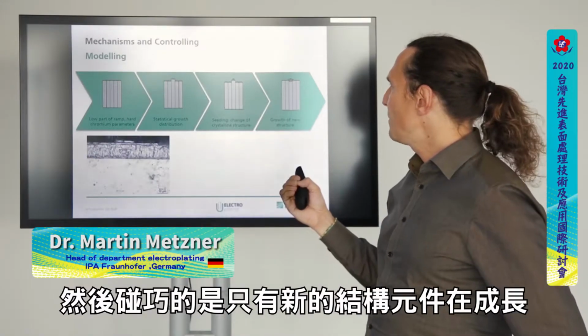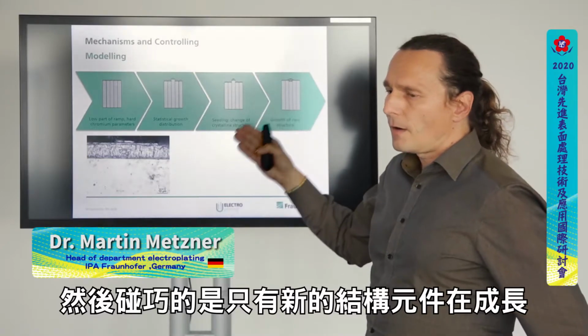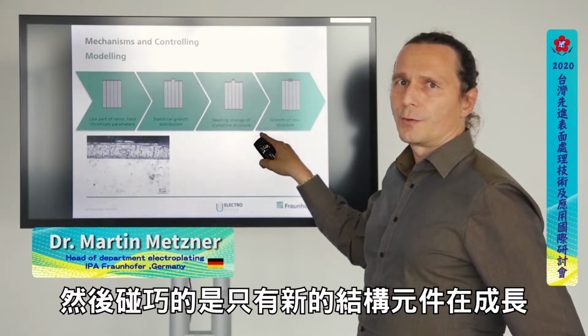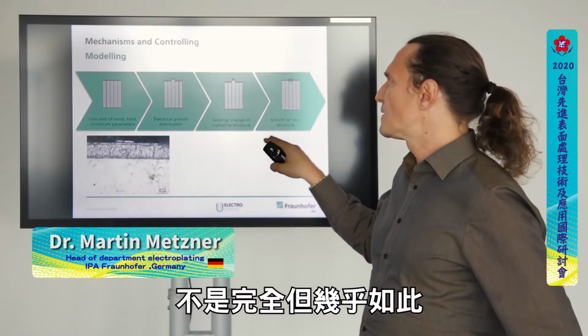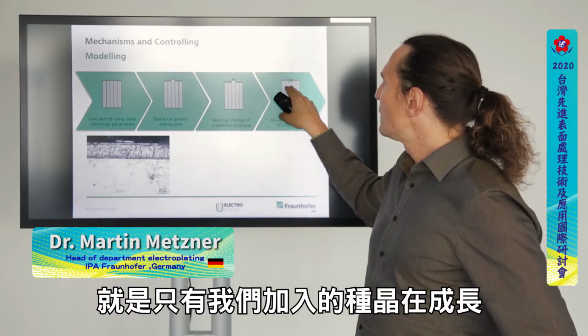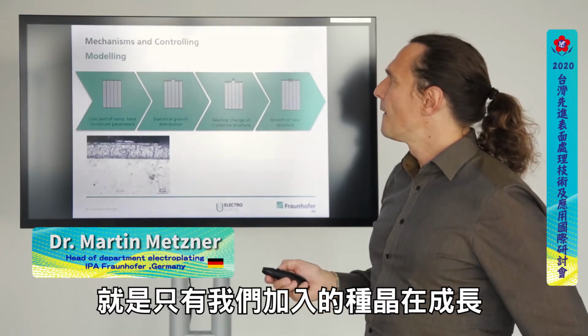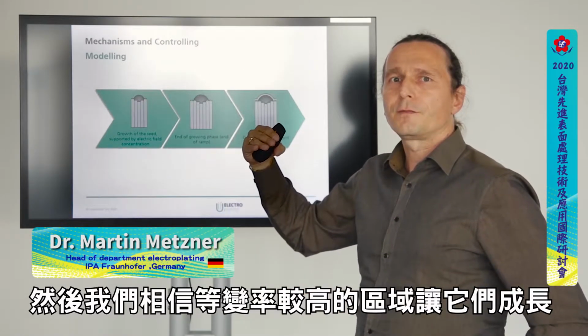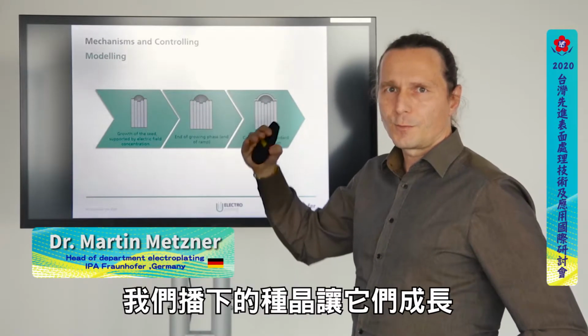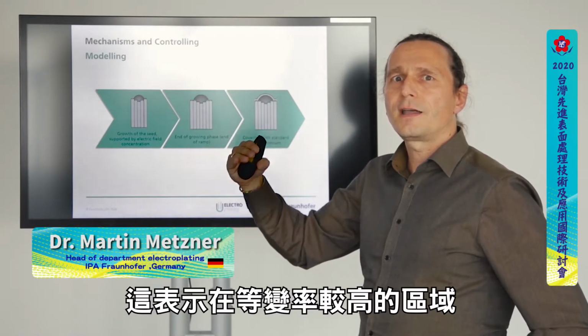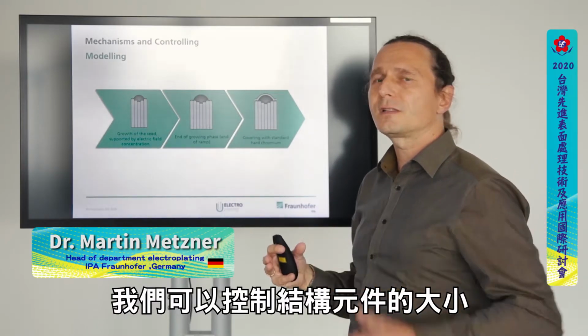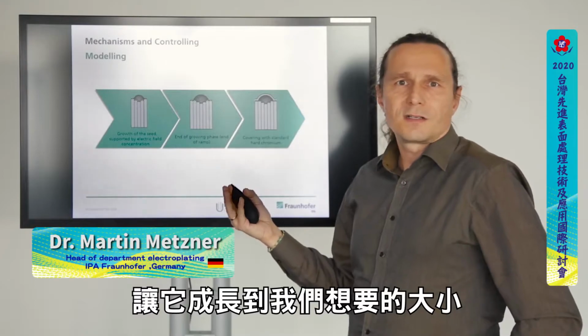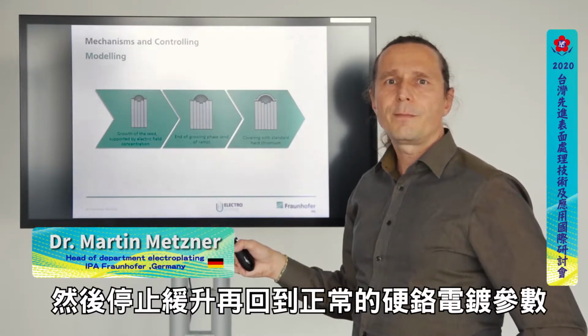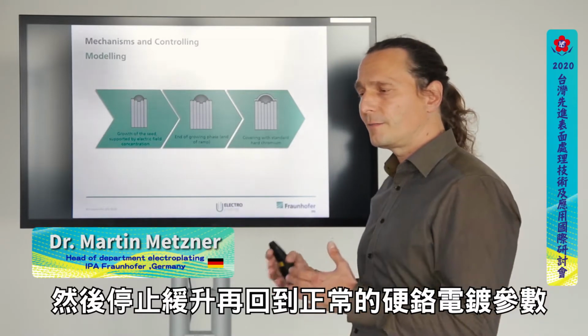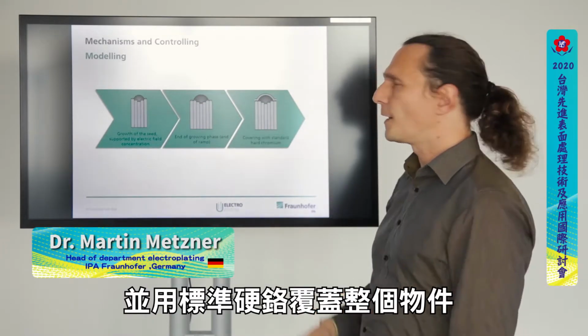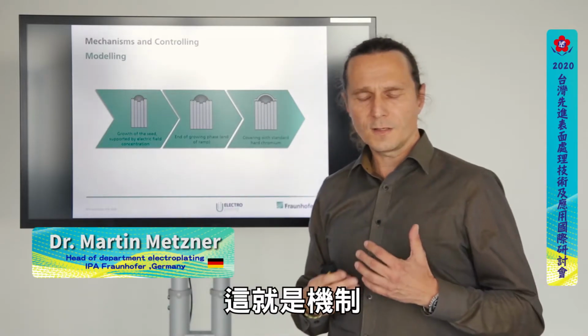And then it just happens that more or less only the new structure element is growing. Not completely only, but almost only. And this means that only our seeds are growing anymore. And then in the higher area of our ramp, we just let them grow. What we have seeded, we let them grow. This means in the higher area of our ramp we can control the size of our structure element, let it grow until they are as big as we want them, then stop the ramp, go back to the normal hard chromium plating parameters again, and cover the whole thing with the standard hard chromium. So this is the mechanism.